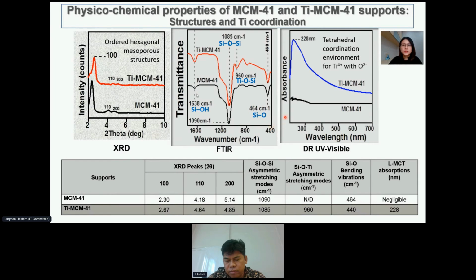Okay, so for this UV-vis analysis, it shows an intense peak for this modified silica support, which indicates the presence of these tetrahedral coordination environments for these titanium cations that are incorporated into this oxygen anion. While for this pure MCM41, it indicates the absence of the metal-to-ligand charge transfer within these hexagonal mesostructures, because of the absence of this intense peak here.